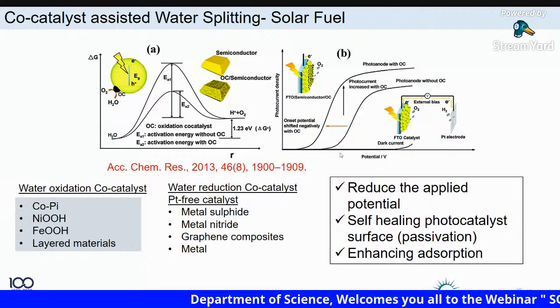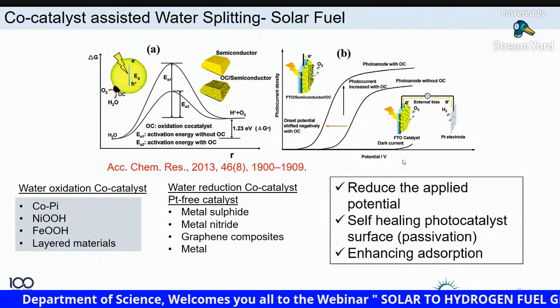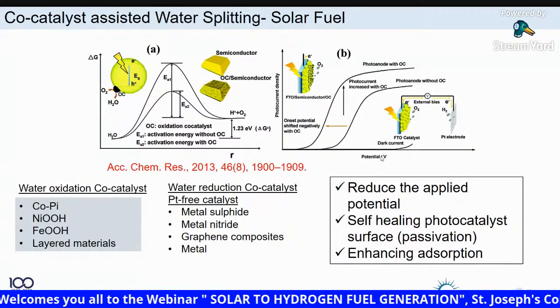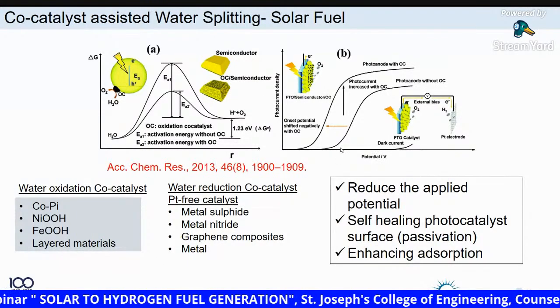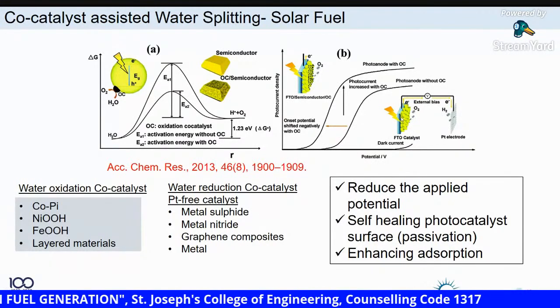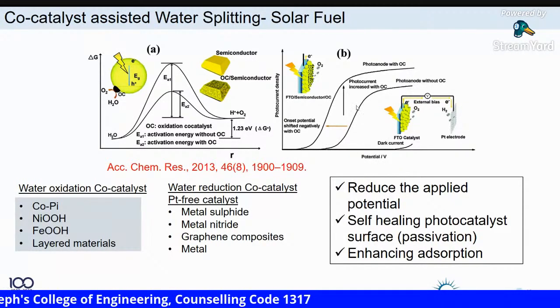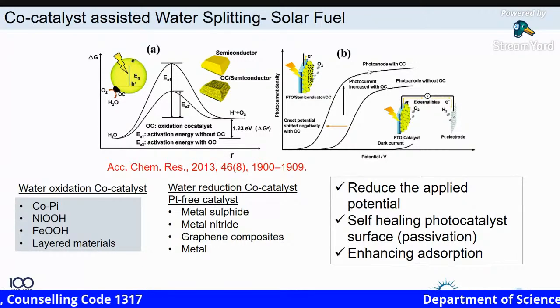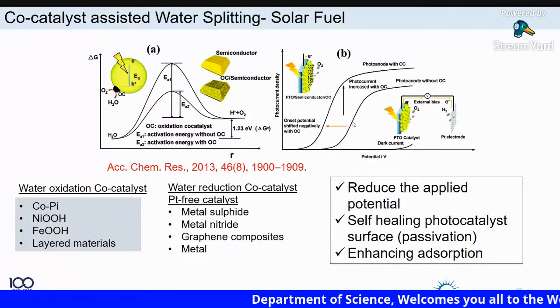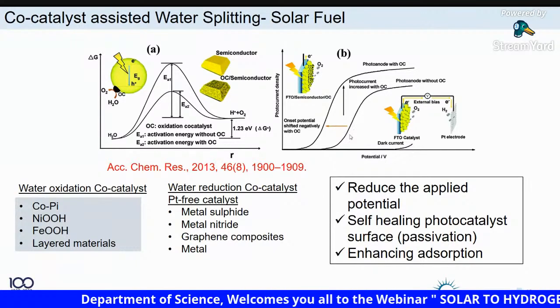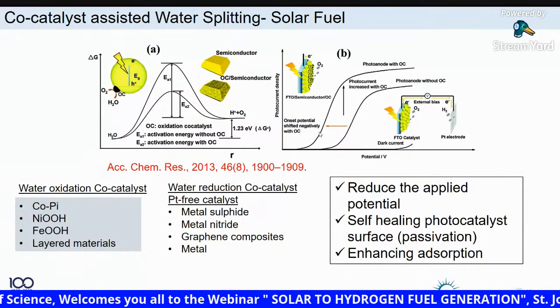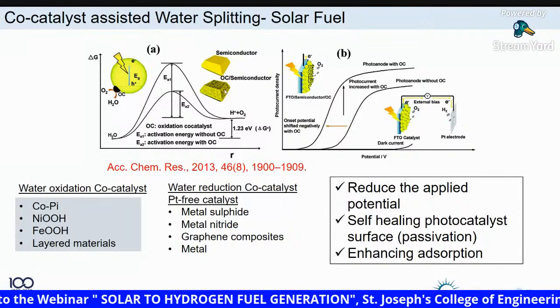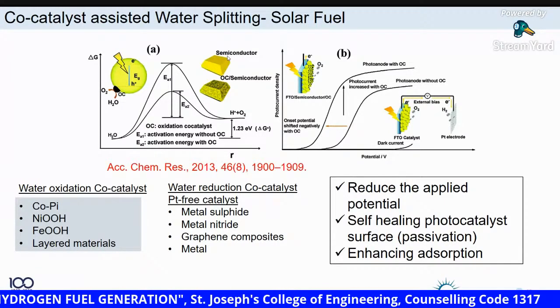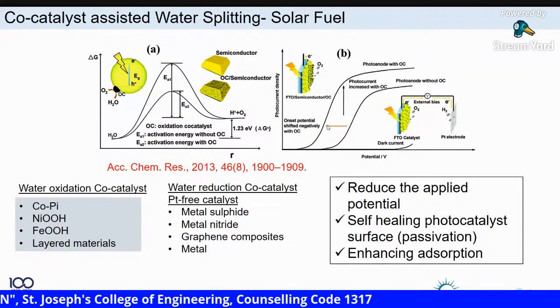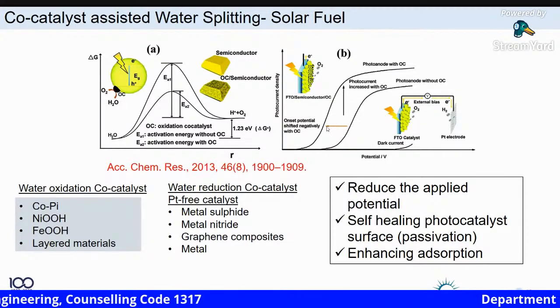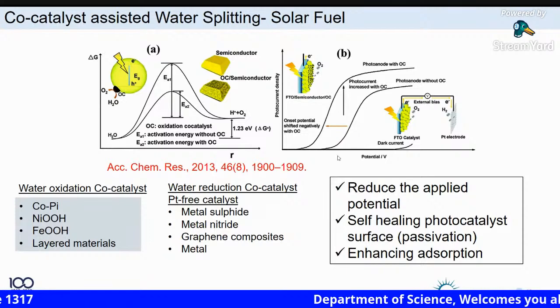Thank you very much. So if you compare the potential versus current density, you can see this is the plot without co-catalyst. After introducing the co-catalyst material, it significantly shifted from the high voltage region to the lower voltage region. So it indicates that when you assemble the co-catalyst material on the surface of the primary semiconductor, it reduces the thermodynamic energy and lowers the applied potential. Obviously, you can save a lot of energy in the circuit.